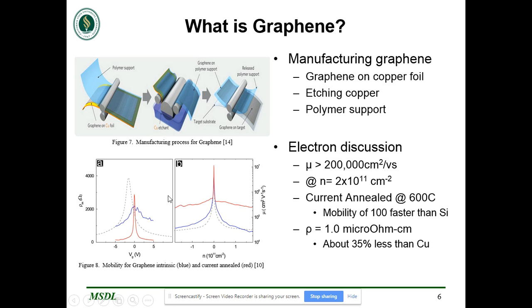But let's look down here for mobilities. We were talking about how cool this stuff is, but look at this mobility, greater than 200,000 centimeters squared per volt second. Now, to give you perspective, you should see mobilities from silicon in the 2 to 3,000 range. So imagine this is 200,000. Mobility is the ability for an electron to move, right? So now you're talking about silicon at 2 to 3,000. I mean, this is 100 times faster. It's 100 times more than silicon.